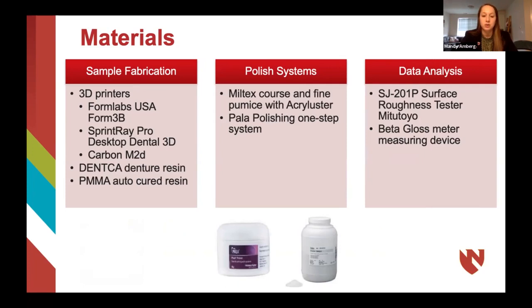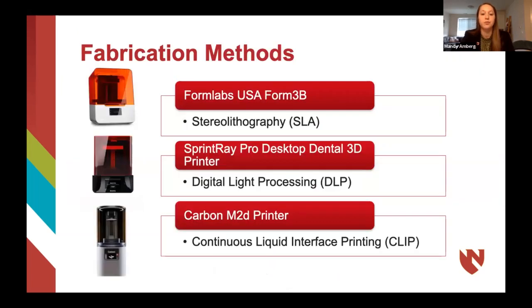2 separate polishing systems were utilized, one being the Pala Polishing one-step system, and the other being Miltex coarse and fine pumice with Acryluster polishing system. To analyze samples and collect data, a surface roughness tester and a gloss meter were used. Each of the 3 printers we utilized uses different additive manufacturing technologies to fabricate the samples. Formlabs uses stereolithography, SprintRay Pro uses digital light processing, and Carbon M2D uses continuous liquid interface production.